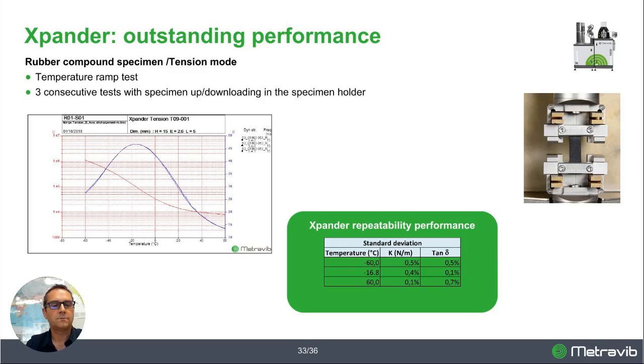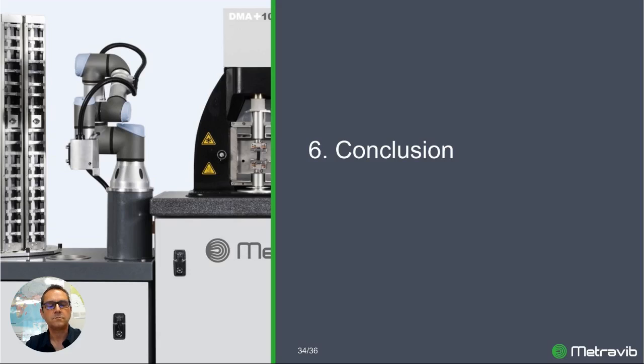And here is another test, in tension mode in this case, with 3 consecutive tests as well on a temperature ramp test, to give an idea. Here we have a much softer specimen than in shear, of course, and you can see that the standard deviation we get on the stiffness is inferior to 1%, and as well for tangent delta.